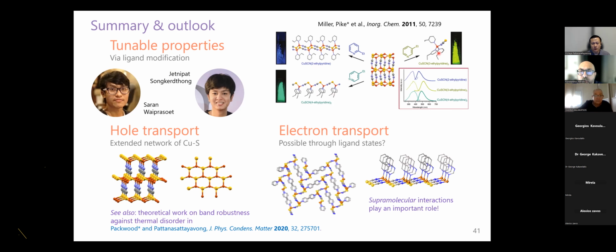Like this is an example of another group. So when they modify with the aromatic ligands, actually can also tune the optical properties. Copper thiocyanate is good for transparent electronics, very large band gap, very transparent, but maybe it's a bit boring. But if we add some aromatic compounds, we can also tune the light absorption and light emission of the copper thiocyanate. And also this two-dimensional network of the copper and sulfur is of interest, and also the two-dimensional layers of the copper thiocyanate structures themselves as well.